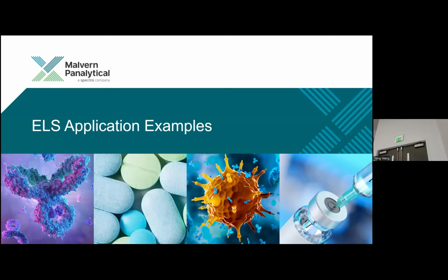Yeah. So, if I got a negative zeta potential, based on your experience, what does that negative zeta potential indicate in general? So it depends. The negative means just the electrostatic environment presents a negative charge around your particles, right? But then the other part of that is, what is the value of that zeta potential? Is it -5 or is it -45? If it's -45, you've got something that's really colloidally stable. It wants to stay in solution for a long period of time. If it's -5, then you might be looking at things that aggregate very quickly. Again, it's the two-part combination: the value and the charge.